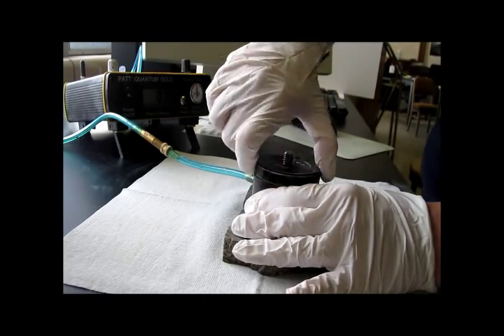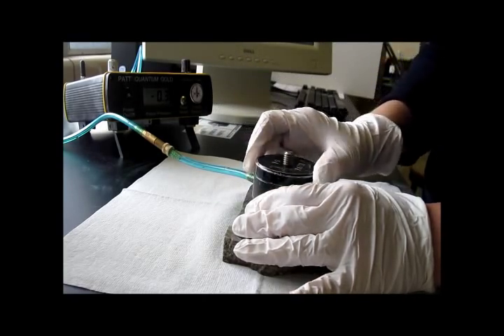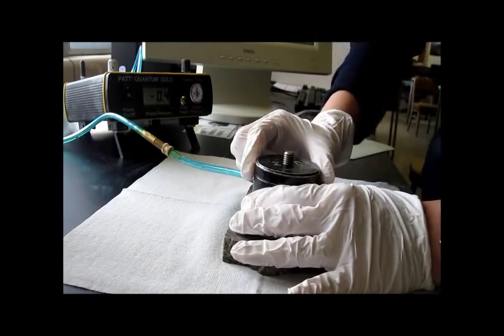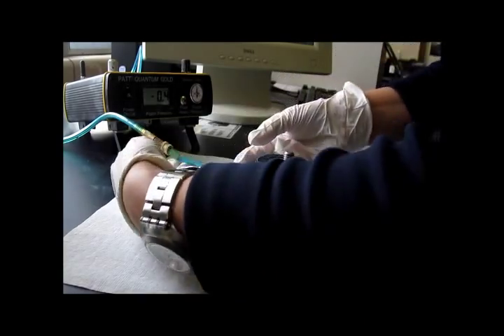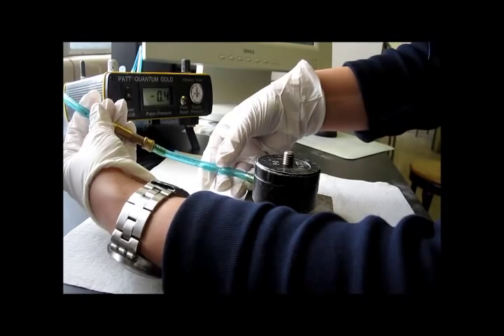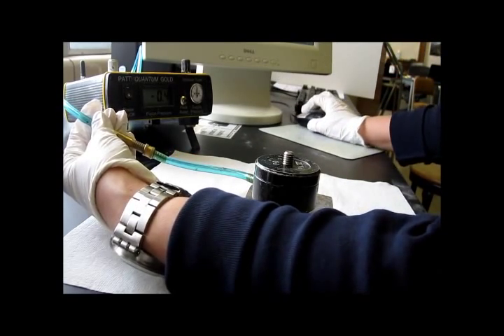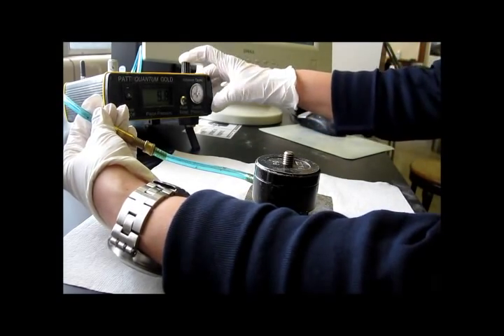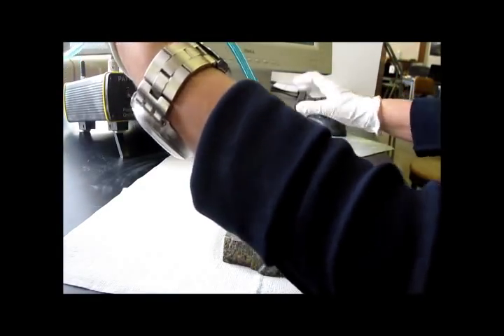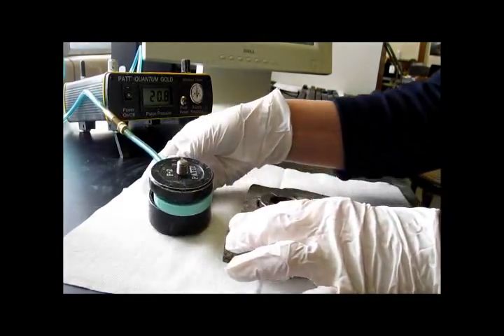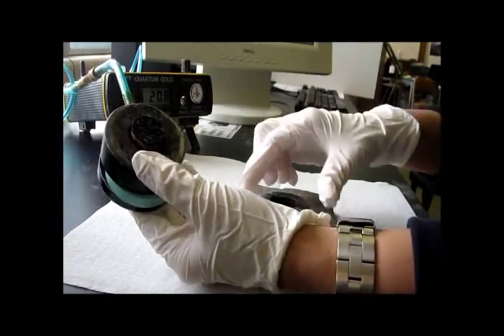Unscrew the pressure plate one quarter of a turn to ensure a small gap between the pressure plate and the pressure ring. Test the samples using the adhesion testing device in accordance with the manufacturer's recommendations. Record conditions such as temperature and humidity for all tests. Record the maximum pullout tension and observe the failure mode.